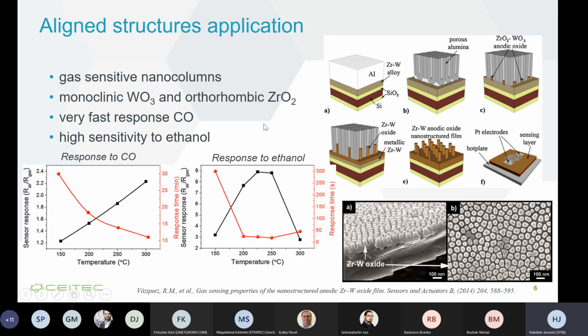Here we created mixed bimetallic nanostructures with monoclinic tungsten trioxide and orthorhombic zirconium dioxide. With these structures created by this template-based technique, we obtained a very fast response to CO and high sensitivity to ethanol, for example, in these results.